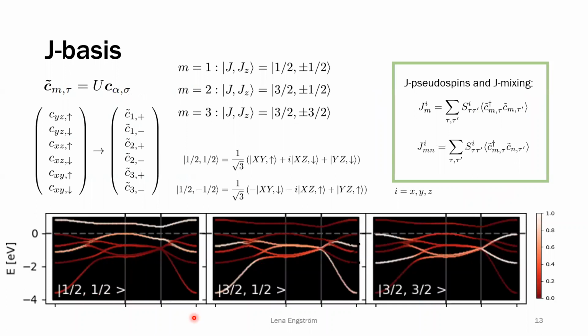So the main point about going into this other basis, which we'll see here, is that we get different projections. Instead of looking at the basis that is the eigenstates of the spin-orbit operator, we can look at this total angular momentum J basis. We basically have what we call M1, M2, M3 here, which are the two subspaces J equals 1/2 and J equals 3/2, where you can have this J_z that's 1/2 or 3/2. And for example, we can see that the 1/2, 1/2 state has equal contributions between the three different orbitals and different spins. And if we instead project eigenstates onto the band structure for this basis, we can see that, since we have a much lighter color here,